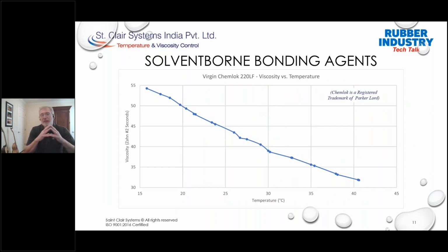For instance, here we see the viscosity versus temperature curve for Parker-Lord's Chemlok 220LF, which is a common solvent-borne bonding agent. And this was measured in St. Clair Systems India's lab. It's the typical curve we're all familiar with, okay? The viscosity is falling as the temperature increases, and though it looks like a linear relationship with a slope of about 0.9 seconds per degree C,